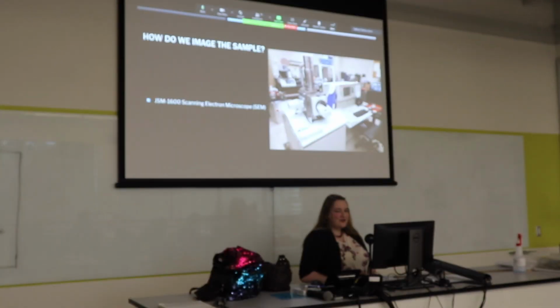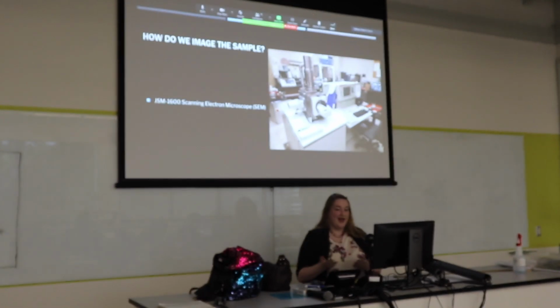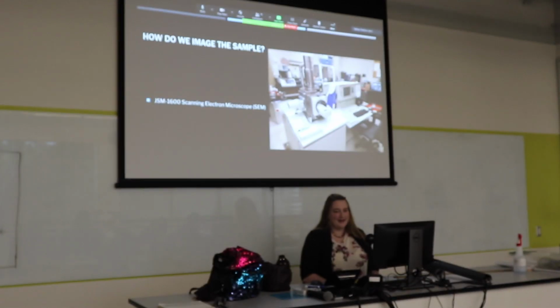So a lot of my research is working with things that are very small and we can't actually see if we've made a difference, like did we actually texture the surface of the silicon. So we image these samples using a JSM 1600 scanning electron microscope, often called an SEM. This is the one that is in Dr. Friedfeld's lab, and a lot of my research was just imaging the different samples in between steps so that we could see what it looks like.